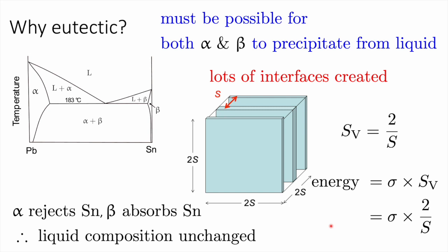So just to summarize, a eutectic happens rapidly because the diffusion field is localized at the transformation front, and you don't enrich the parent phase when the eutectic grows from the parent phase for a binary system. But the cost of creating interfaces means that the interlamellar spacing between the alpha and beta phases can only be fine if we undercool a lot below the transformation temperature. Of course, this is important because we may want to control the interlamellar spacing in order to achieve a particular strength.